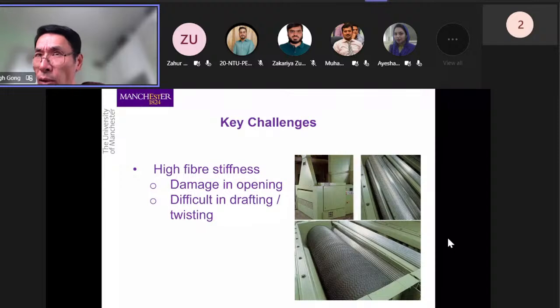The other problem is during drafting, the fibers are too stiff and they're of varying length. So they are not really moving very well, because drafting obviously requires us to control the fibers so they move as they're supposed to, so we can deliver a strand with even distribution of fibers. So in the end, you will find that drafting carbon fibers becomes very hard. So a lot of people, as we will see again later on, use mixing methods by mixing carbon fibers with other fibers. That way we can use the other fibers as carrier fibers to help the carbon fiber through the drafting process.